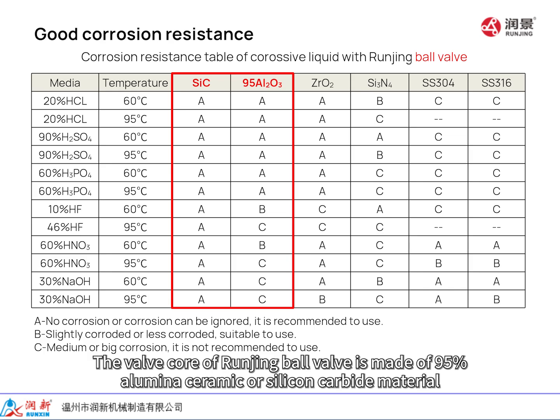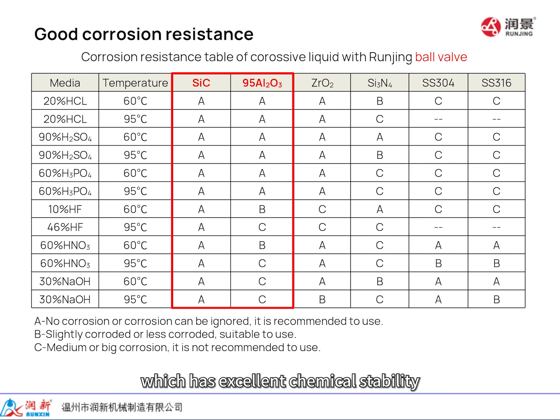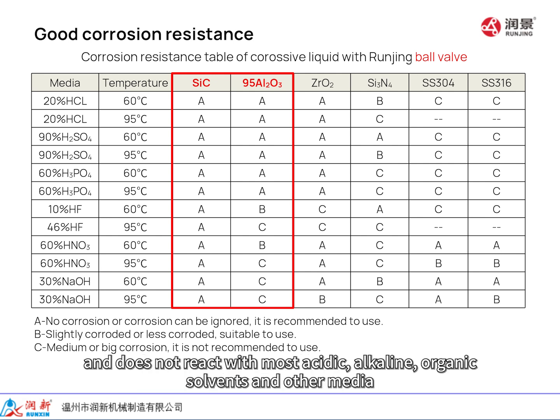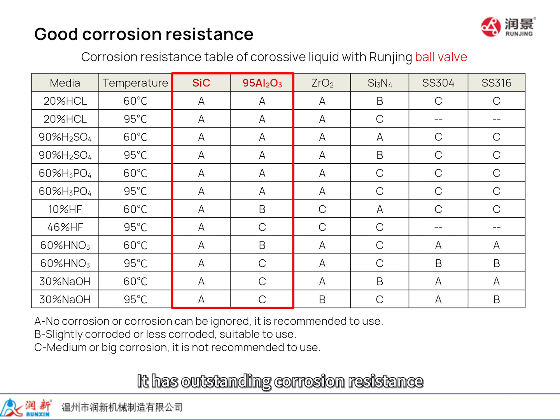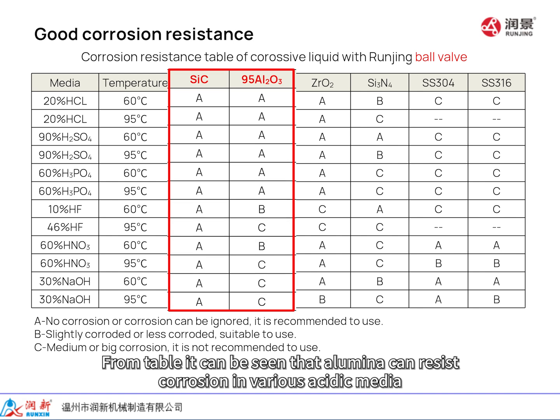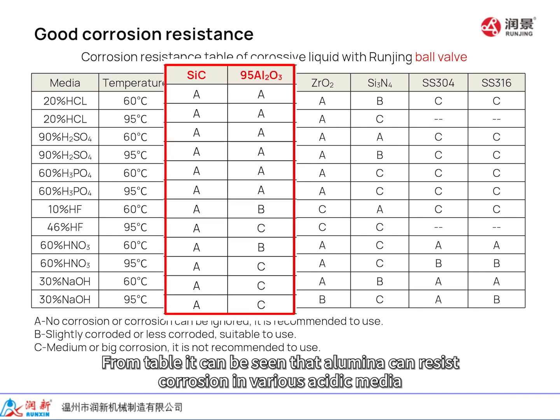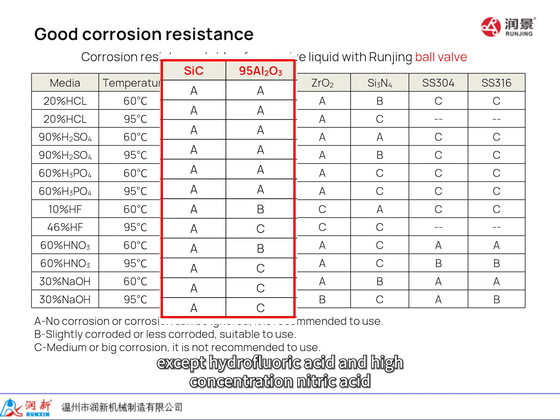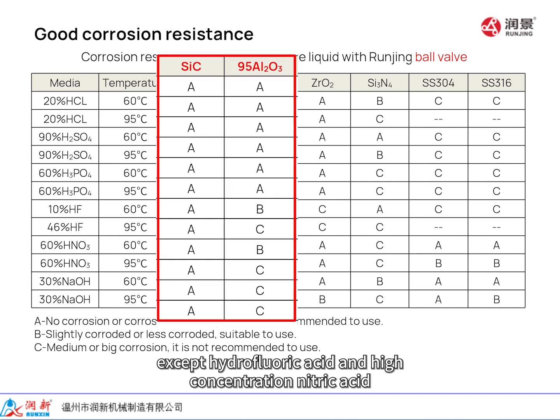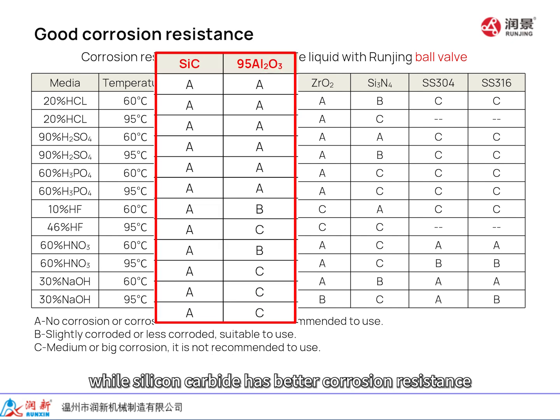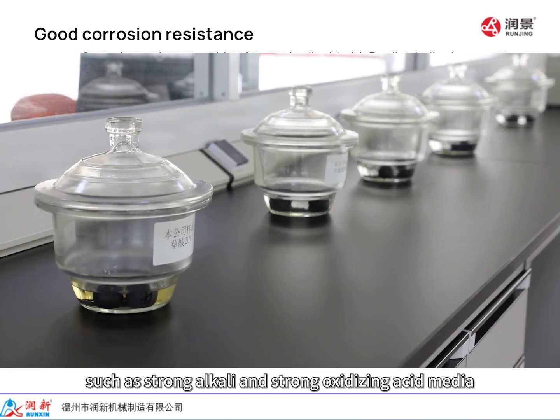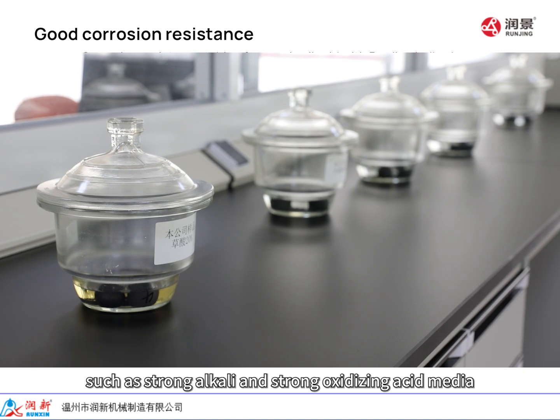The valve core of Runjing ball valve is made of 95% alumina ceramic or silicon carbide material, which has excellent chemical stability and does not react with most acidic, alkaline, organic solvents and other media. It has outstanding corrosion resistance. From the table it can be seen that alumina can resist corrosion in various acidic media except hydrofluoric acid and high concentration nitric acid, while silicon carbide has better corrosion resistance, such as strong alkali and strong oxidizing acid media.